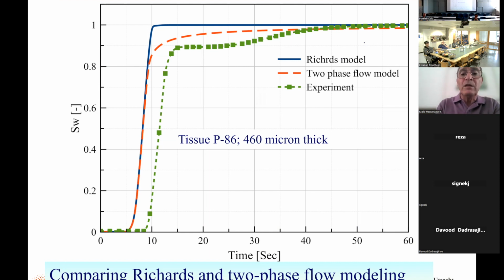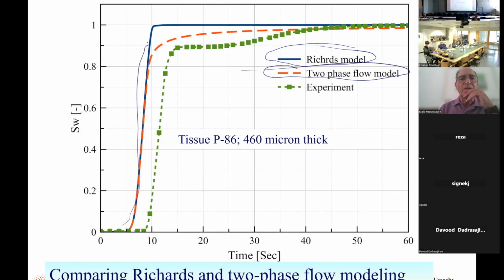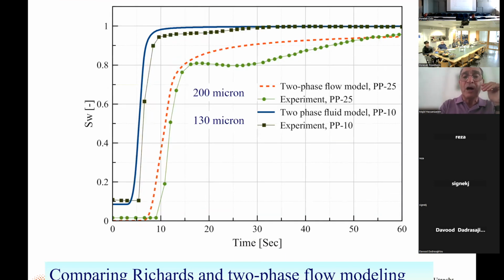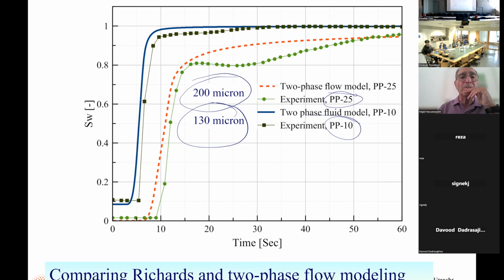And you can simulate it with Richards' model, having only saturated flow. But you can also say, yeah, but the air is under pressure, therefore it takes time. We know how long it takes to reduce the air pressure, because it doesn't happen in zero time, to some very low value. It takes some time, so we include that, and so we do a two-phase flow model. Both of them really give you the same curve, and it's different from the measured data. This was one type of tissue, and then we did it with two other types of tissues. They were a little thinner. And so again, the symbols are the measurements and the curves are the simulations. We don't get a real nice fit.